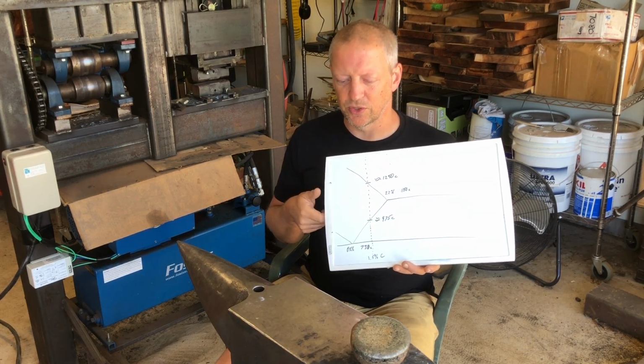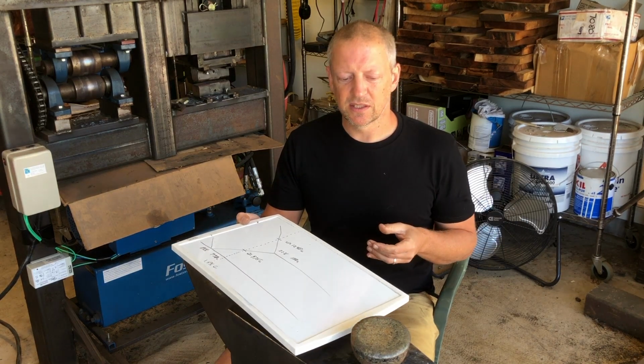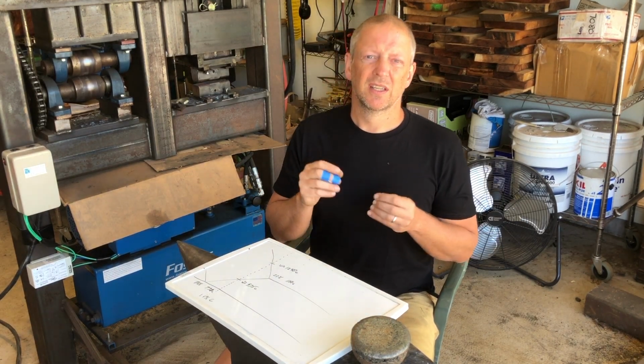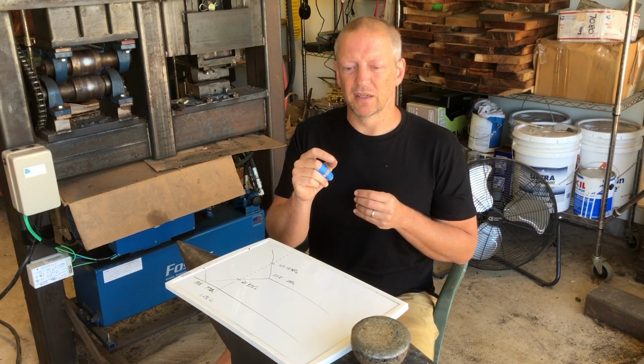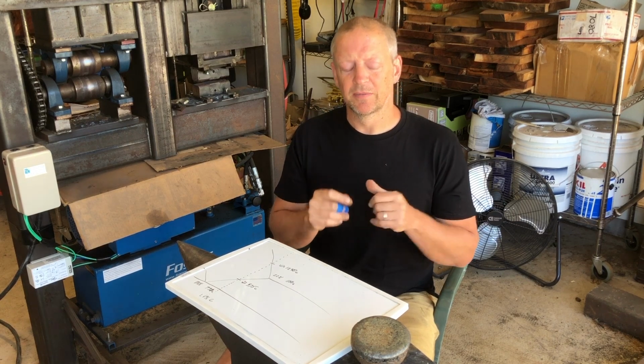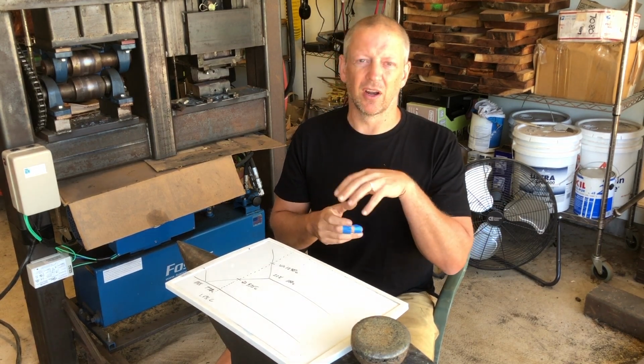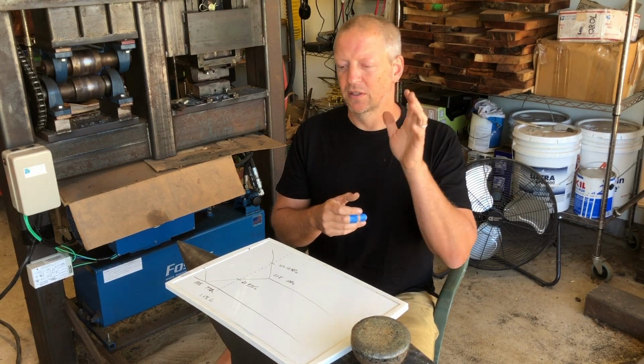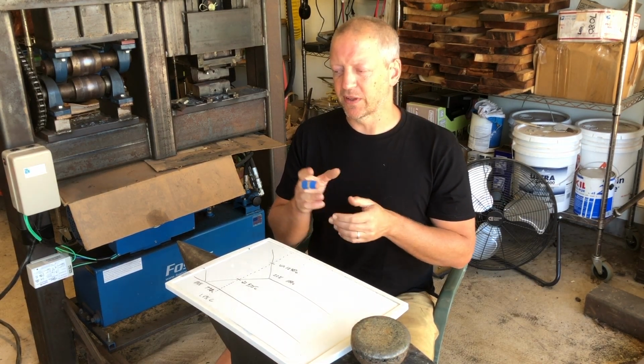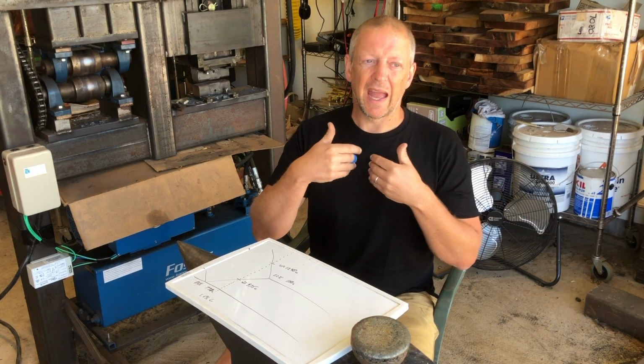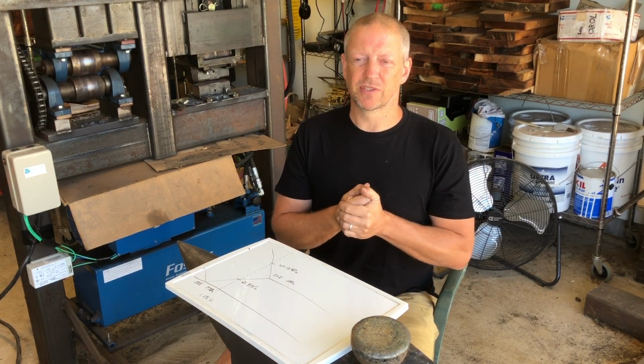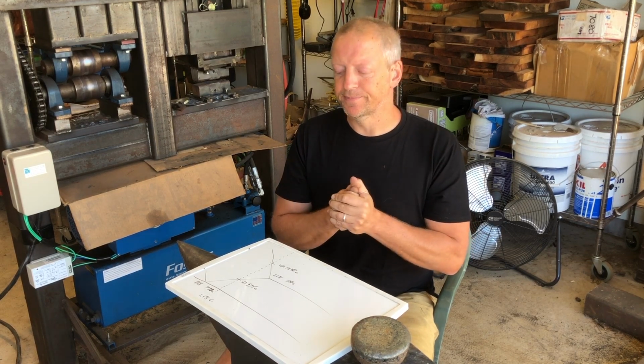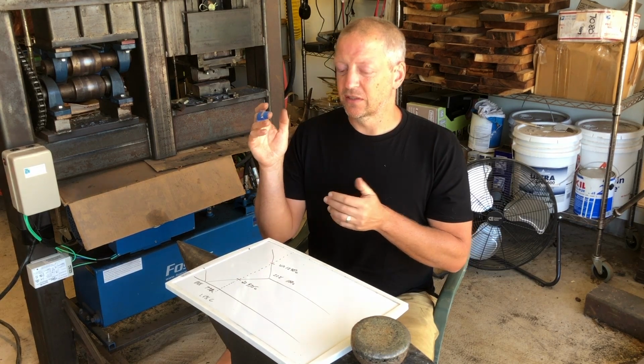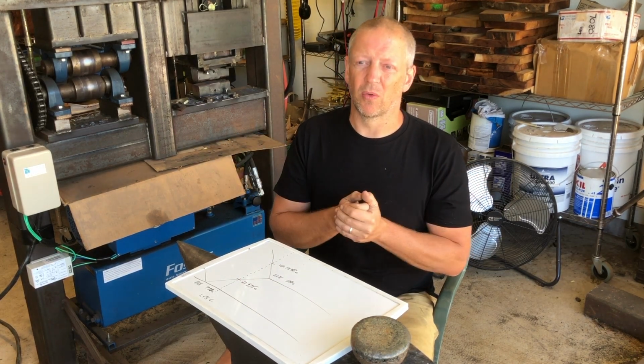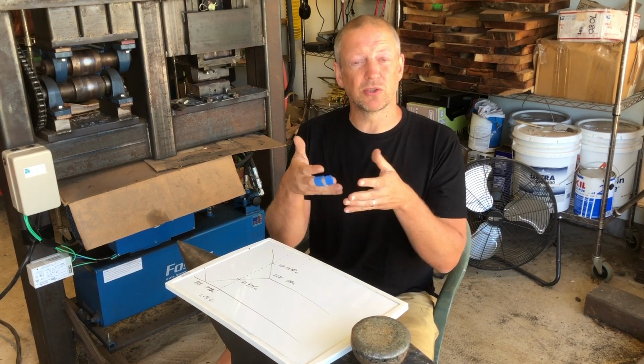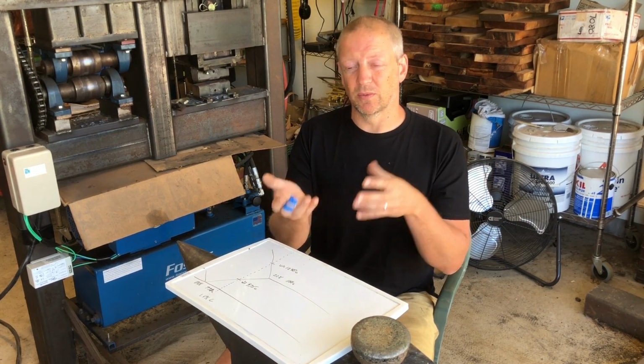Now the second item I'm going to talk about quickly is nickel. You really don't want to add any appreciable amount of nickel into a very high carbon, hypereutectoid steel. And the reason for this is, again, graphite. Nickel actively pushes carbon out of solution to create graphite. Now, that's obviously not a good thing. We don't want graphite, and any carbon we lose as graphite is carbon that doesn't get to become carbide.